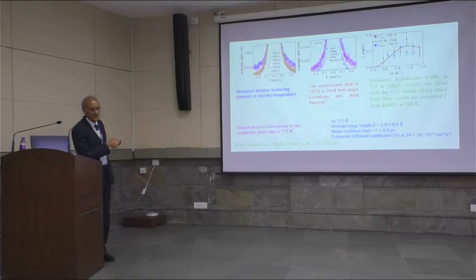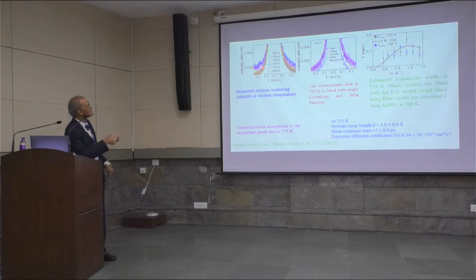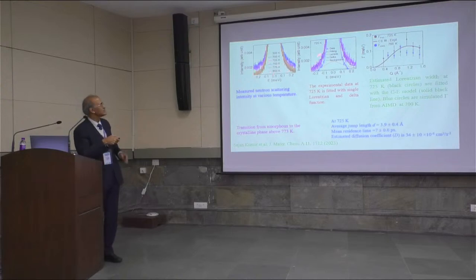this is data of the quasi-elastic neutron scattering. So the elastic line, we have just shown the tail part of it. You can see that with the increase in temperature, this is at low temperature, you have essentially only the resolution of the instrument. As you increase the temperature, there is a broadening of the elastic line, and you have some increase in the intensity also because of phonons, but that can be accounted for. So this is fitted to a Lorentzian kind of function. And the width of this Lorentzian function is plotted as a function of the momentum transfer. Okay, and then this is fitted to certain kinds of models.